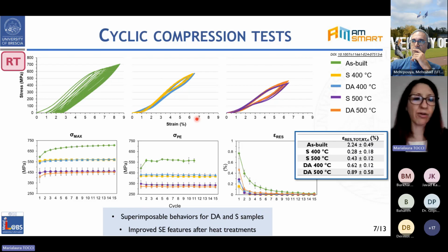This is further confirmed if we have a look at the data of stress and residual strain for each cycle, and especially the residual strain after all the experiments. It is evident that after heat treatments, this residual strain is much lower as compared to the as-built condition. So in any case, the treatments are effective in improving superelastic features.